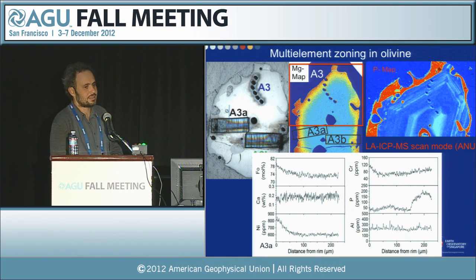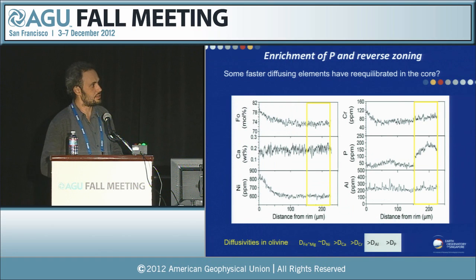You can see this is not as sexy as using an ion microprobe. I mean, you have a lot of noise here, and it's not as good, but still you can see the profiles, the trends relatively well. Basically I see two main features. I was showing you this high phosphorus zone that occurs in the core next to the skeletal part, and aluminium doesn't seem to care. Chromium might care, it's kind of decreasing. Forsterite, calcium, and nickel, they don't care.